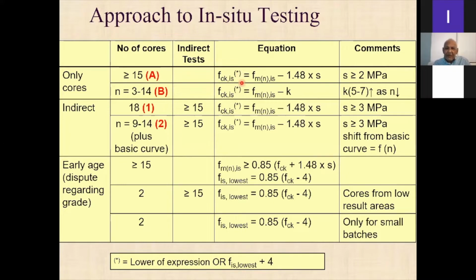So here, this is the estimated in situ characteristic strength. That's the way it's done if you're looking at an older structure, right? You are not checking the grade. You are checking the grade only here, that is early age, right? So here, you take, typically, something like this. And then here, if it is less than 15 cores, you get the in situ mean strength